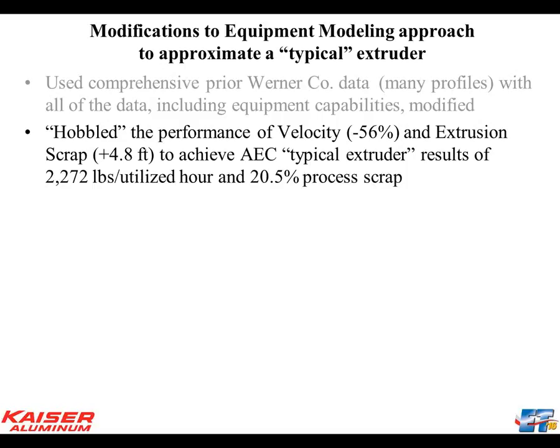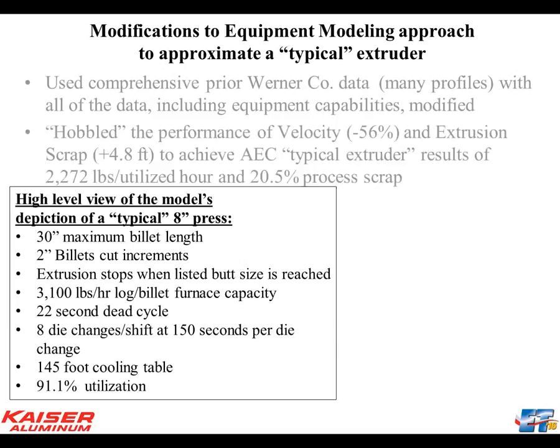We were always known as a very fast extruder, cold and fast. But I hobbled the velocity and I added a little bit of scrap in order to achieve the typical extrusion, 2,272 pounds per hour and 20.5% scrap. I did this modeling what I felt might be a typical 8-inch press, 30-inch maximum billet.